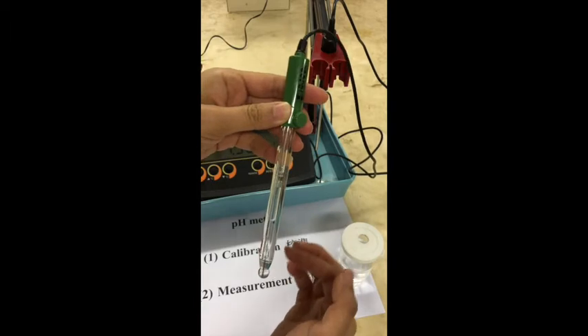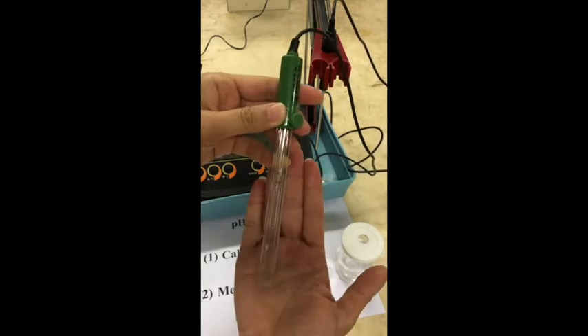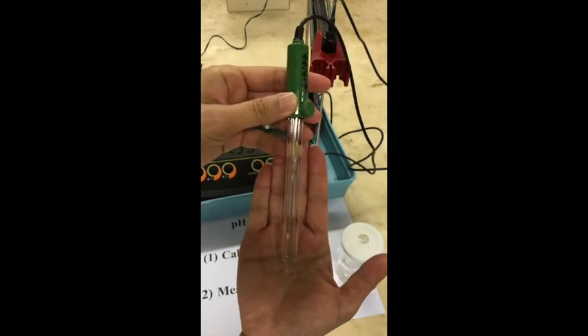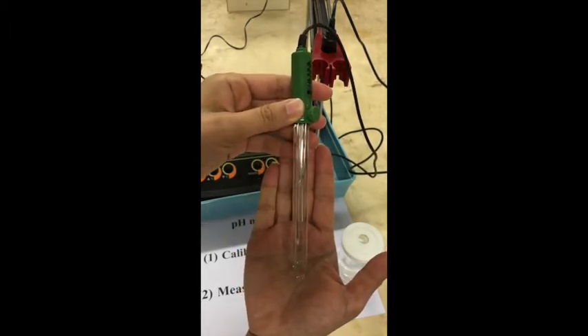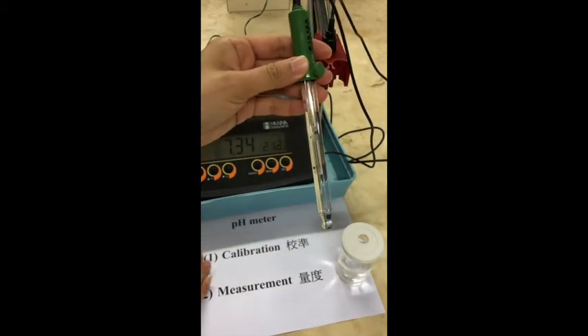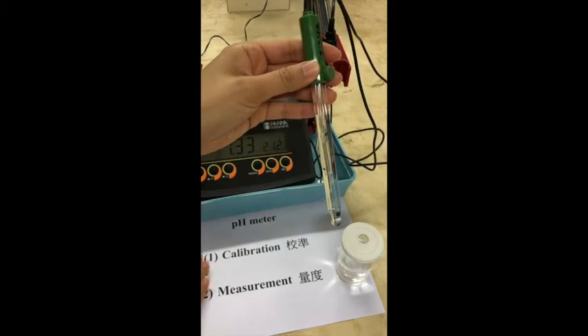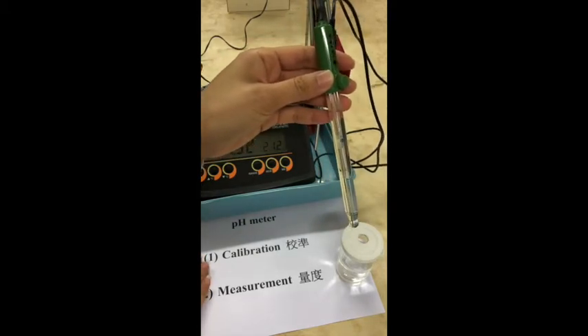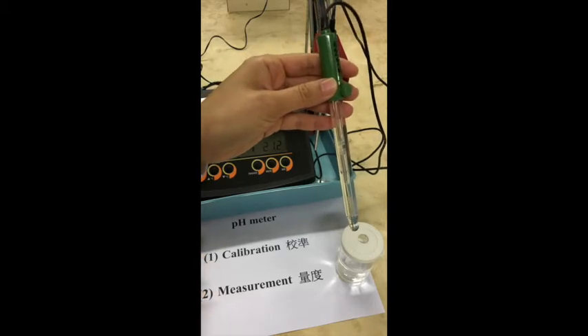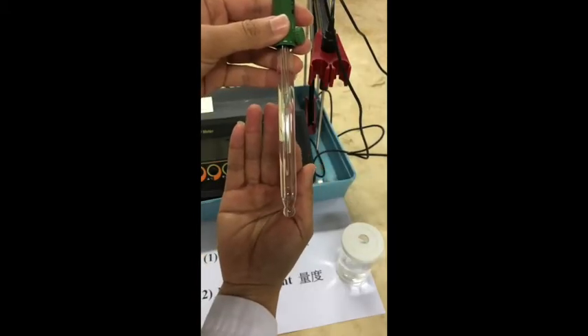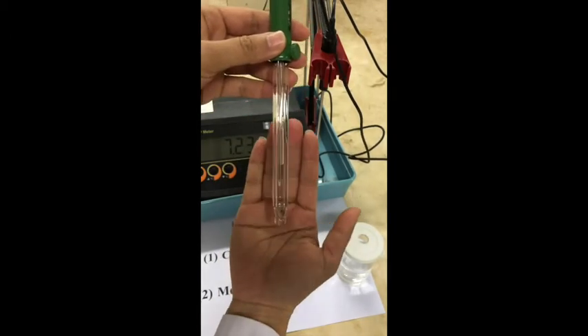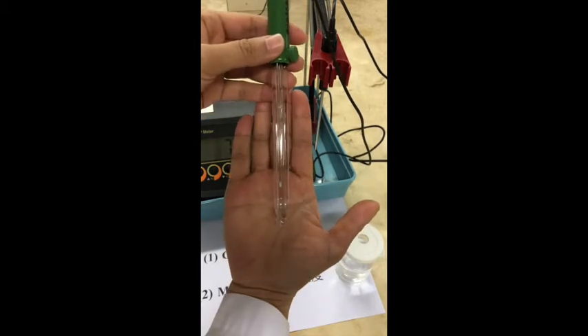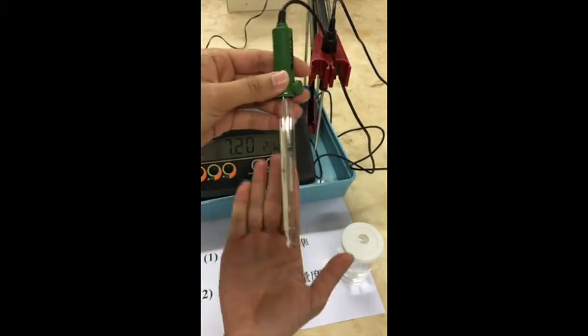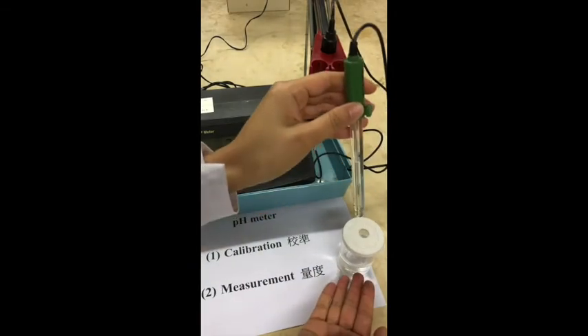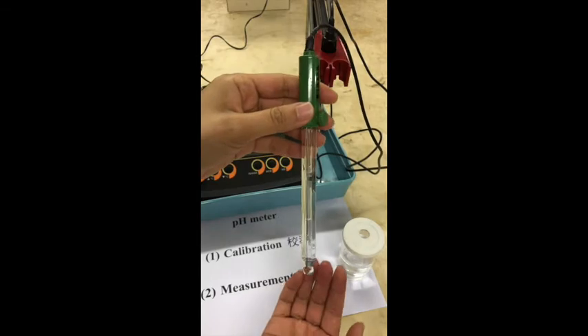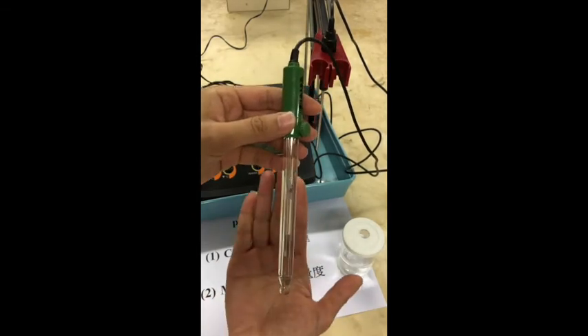The electrode potential of the probe depends on the condition of the boundary of the glass and the solution inside the probe. The calibration has to be conducted if the pH meter is switched off or idle for a long time, as the condition of the probe may change. The liquid level inside the electrode will be lower if the glass is dry. That's why we have to place the electrode inside DI water when it's idle. If the liquid level changes, the electrode potential of the probe also changes.